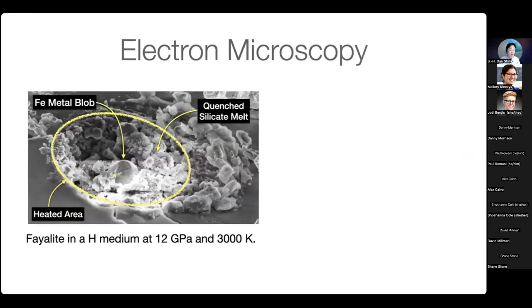So to summarize this experimental observation, I'm putting this electron microscopy image of the heated area back, but this is from the angle, not from top down view, so that you can actually appreciate more of what happened during the extreme melting event of silicate and metal, under hydrogen atmosphere, or in this case, hydrogen liquid, because pressure above 5 GPa makes hydrogen into liquid state. You can see again the metal sphere at the center with a little bit of holes you can see at the top of the sample, surrounded by mostly oxide that lost the silicon and oxygen. Silicon went into the metallic iron and oxygen got released to the hydrogen and formed water.